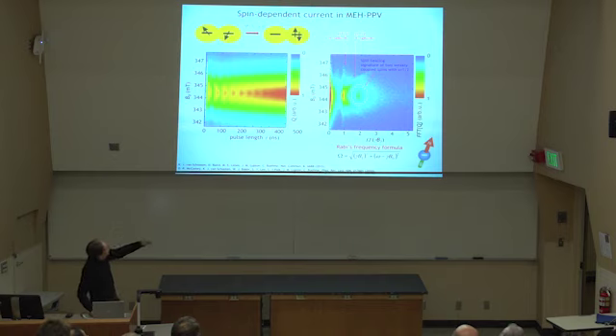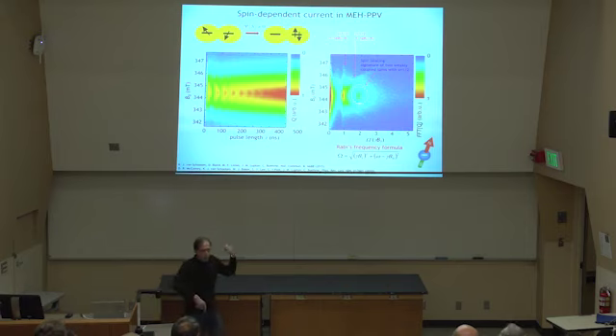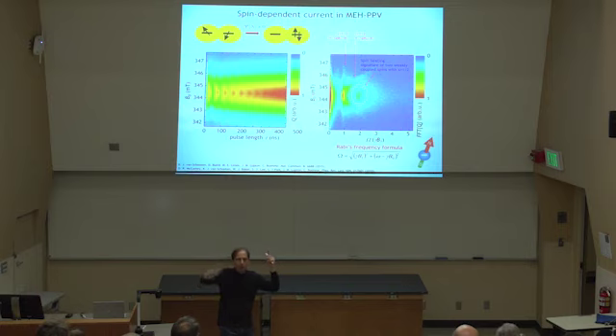What you see here, kind of the revealing feature, is this factor of 2 spin beat oscillation. That is simply what you do there: you turn one of the charge carriers, let's say an electron, while your hole sits in a place, and that oscillates at gamma times B1, and that controls your current due to the Pauli exclusion principle. If you do the same with the hole while the electron sits and is not excited, you get a similar signal. That corresponds to these two features.